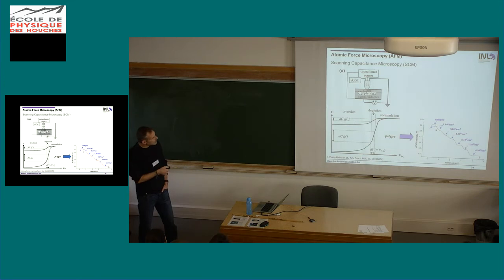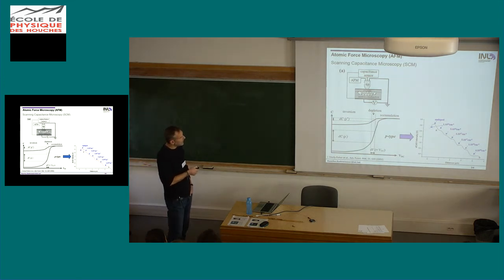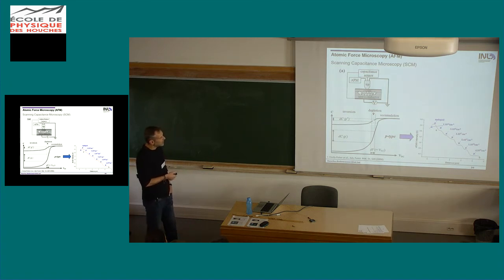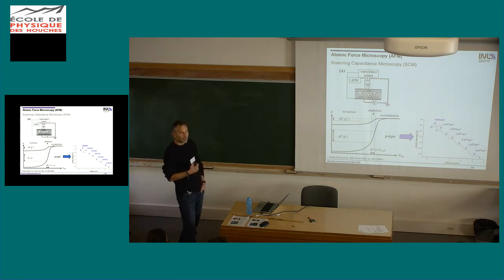So in the microscopy mode, what we do is we use an AC voltage that we apply at some DC bias. So we oscillate between these two lines, and then we can immediately see that the oscillation in the capacitance for the highly doped semiconductor is very small, whereas for the lowly doped semiconductor we get much larger variation in the capacitance. So that means that if we have a large signal, we have a low doping, and if we have a low signal, we have a high doping.